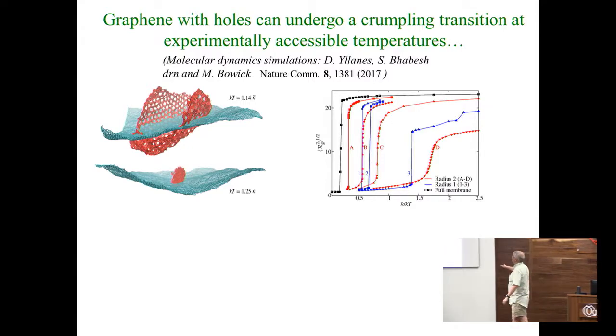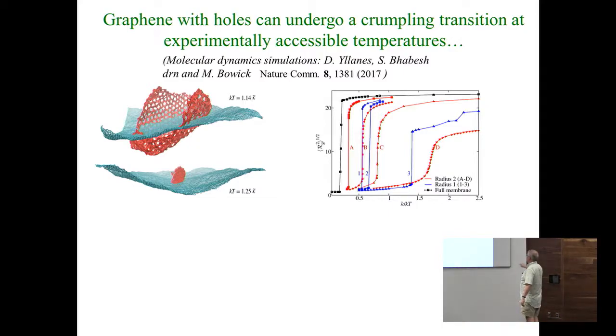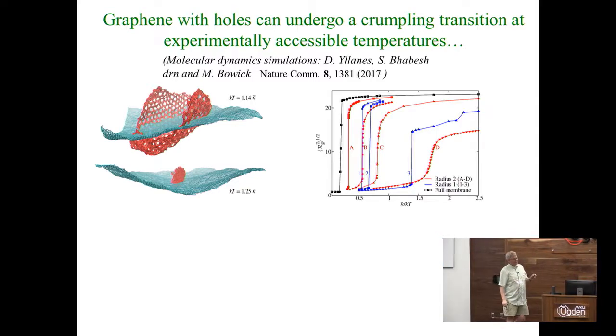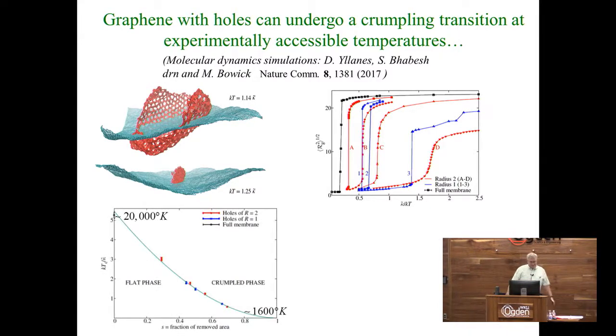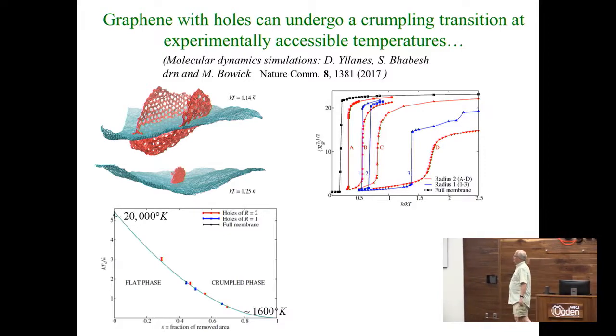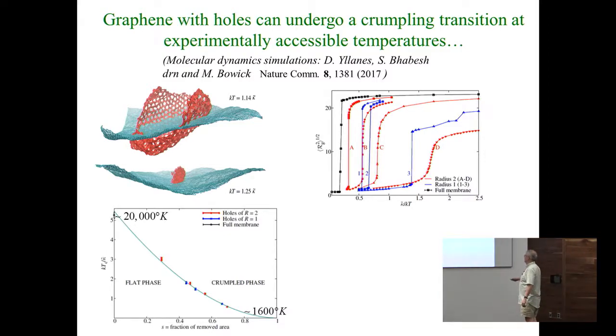This is something called the radius of gyration as a function of the bending rigidity, a rescaled bending rigidity divided by kBT. And there's a dramatic jump in the radius of gyration. At low temperatures, it's flat, so the radius of gyration, let's say, follow this blue curve, is large, and then it undergoes a very abrupt transition as it crumples. And as a function of the removed area, we can calculate the crumpling temperature. It's shown here, and we get this interesting curve, this green curve, and we roughly know it should be dropping once we add the holes, but we don't know the details of this drop.